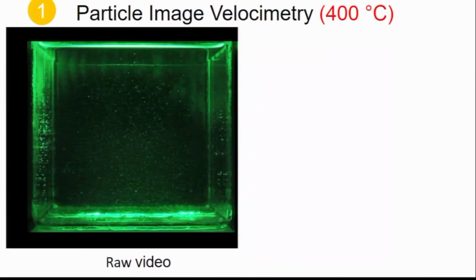Some people have cited the high temperature of the salts, others have talked about the corrosive environment. Well, taking all of this into account, what I was able to do in the lab was actually build this entire setup, find materials that could work with the molten salts in order to perform and to prove the viability of PIV being done on molten salts for the very first time at a bulk temperature of roughly 400 degrees Celsius. And let me show you what that looks like in my molten salt test section.